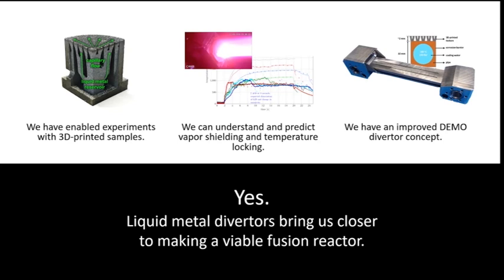Actually, yes, I can tell you about this. There are two things that you need to take care about when you are designing the CPS, and flow speed is actually not number one. What you want to take care of first is flow stability. You have to design the geometry such that the liquid can flow through smoothly without bulging out at any point. So we tested this with just a water flow experiment. We printed a bunch of plastic geometries, with a student, Joep, who did fantastic work on this. And that is why we selected the geometry that we have. The geometry is just a rectangular array of these little tree-type structures.